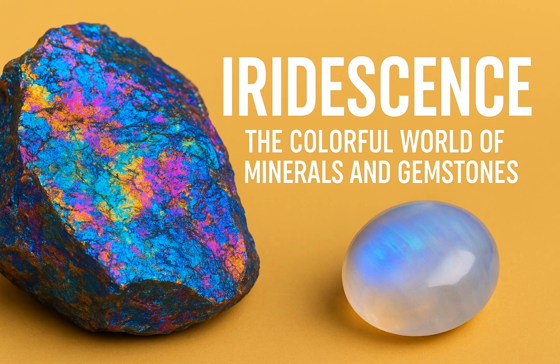These films form as the molten bismuth slowly solidifies and reacts with atmospheric oxygen. Okay. The thickness of these oxide films varies minutely across the surface, creating the thin film interference that produces the spectacular rainbow effect we see. And what about that weird shape? The stepped cubes. That distinctive hopper crystal shape, which looks like a stepped, hollowed-out cube, is a pseudo-cubic habit resulting from this very specific slow cooling process. The edges of the crystal grow faster than the faces, creating that unique, geometric, almost alien-looking structure.